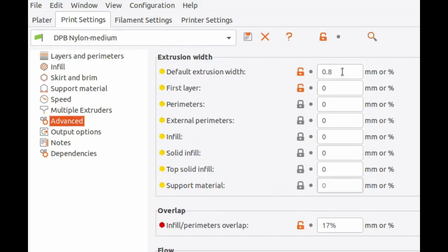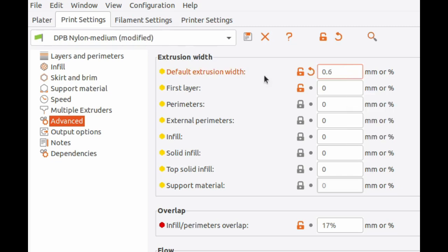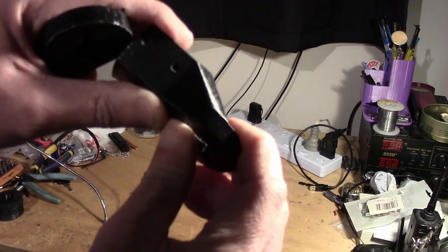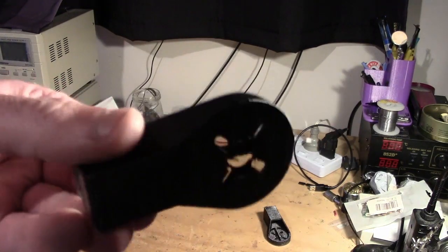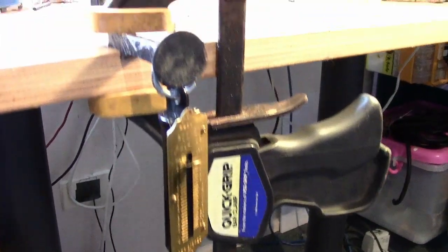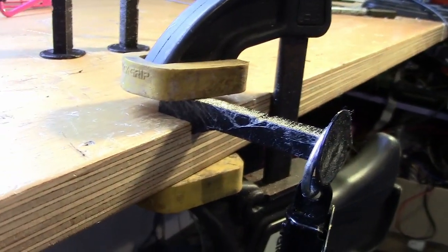Another important parameter to play with is the extrusion width, which effectively translates to the pressure that is applied when printing consecutive layers. For all my functional prints, even with PET, I set this to 1.5 or 2 times my extruder diameter to make sure I get a really strong interlayer bond. The extruder print temperature is one of the other things you can play with that has a big impact on the strength of your print.